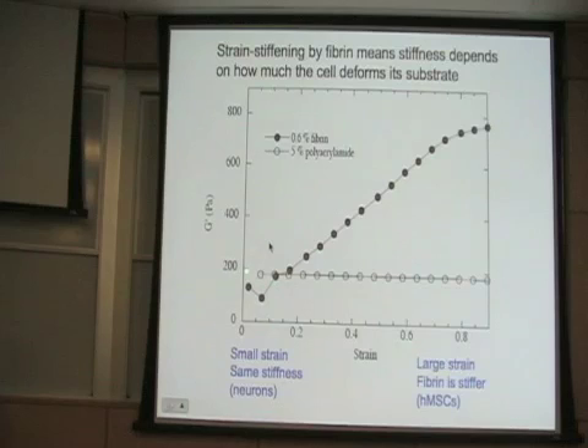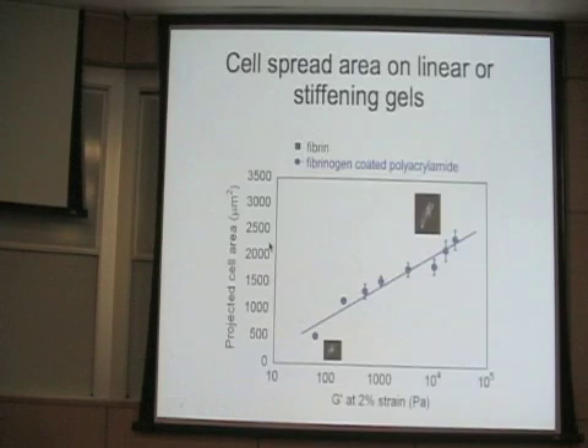So if you have something that pulls a little, and you put it on two materials, for example, a strain stiffening fibrin gel and a linear polyacrylamide gel, if you formulate those gels so they have the same linear elastic modulus, a weak cell like a neuron will see them both as soft. But a hard pulling cell that puts a large deformation on these materials will still see the acrylamide gel as soft because it's linear. Its elastic modulus is the same all the time. But if it pulls far enough to engage the strain stiffening regime in the nonlinear gels, it'll see these as stiff. That's at least the hypothesis. And this is both, I think, borne out by experiments, and it's also a bit of a problem for our attempts to use them